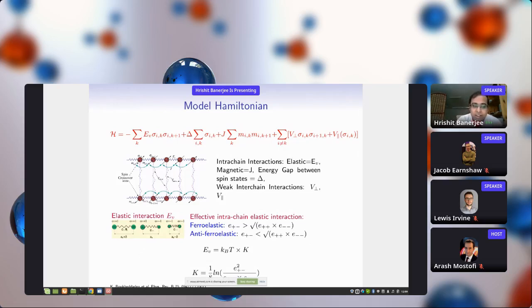Well, the elastic interaction EV is basically spin dependent. And why is it spin dependent? Because the sizes of the high spin and the low spin coordination centers are different, because the volumes change. So the high spin has a larger size than the low spin, and the high spin-high spin pair is E++, the high spin-low spin pair is E+-, and the low spin-low spin pair is E--. And as you see, if you take this distance as A0, then you have A0 plus delta for E++ and A0 minus delta for E--.